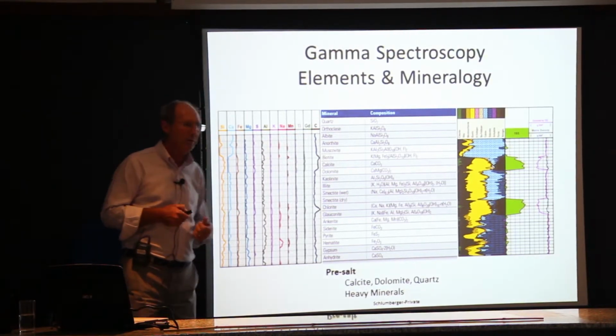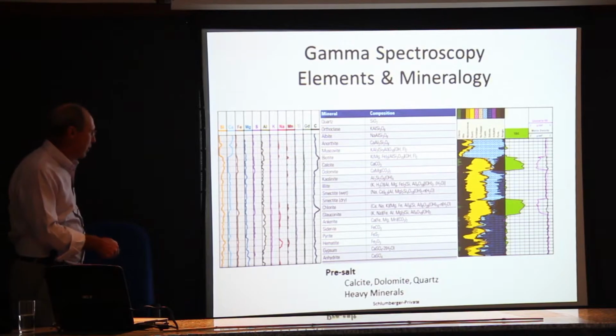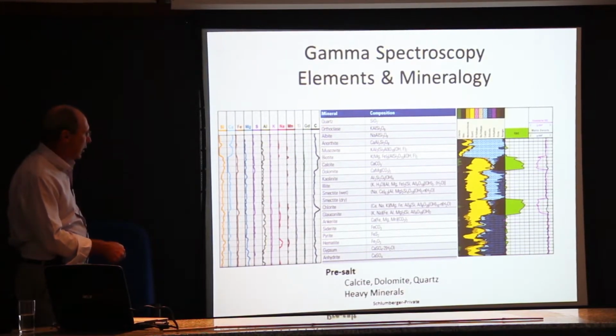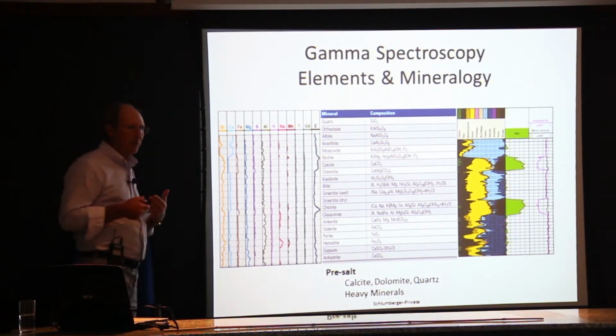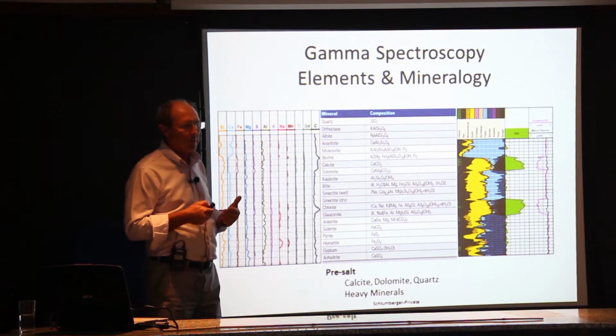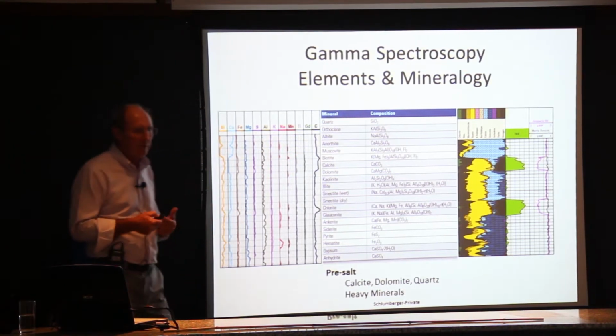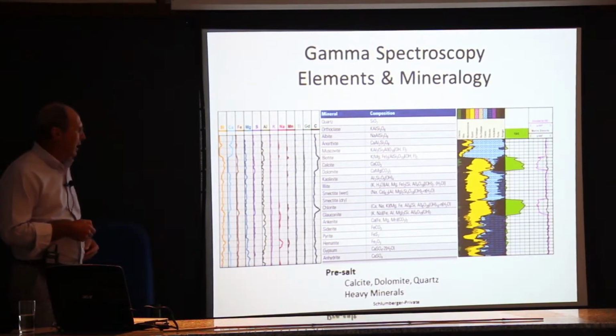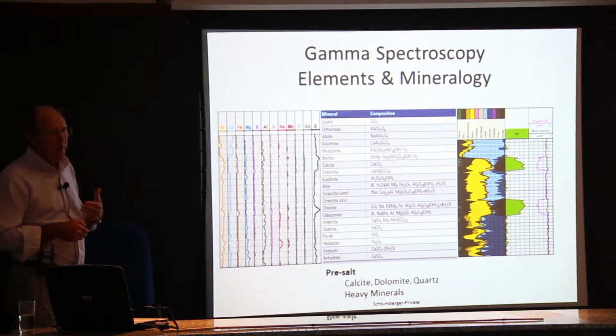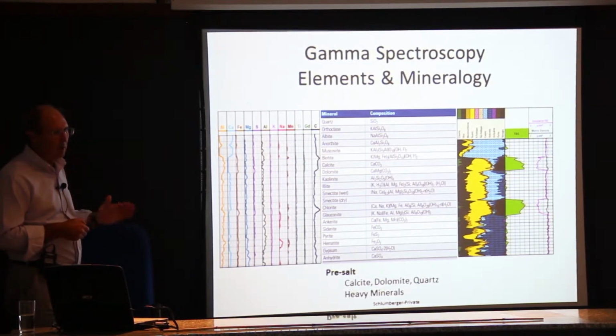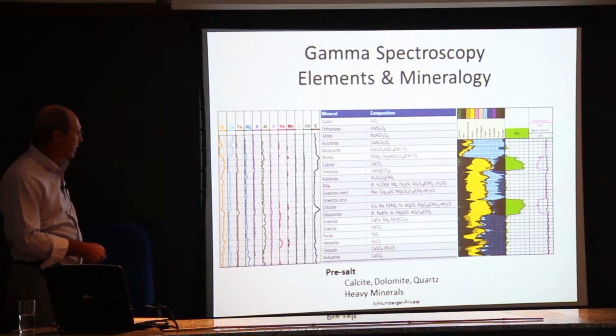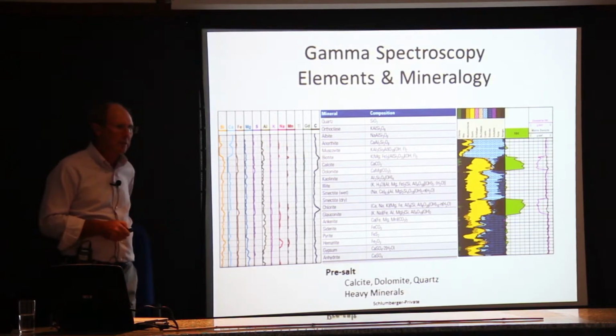Also heavy minerals. Heavy minerals are a big problem in the pre-salt. Siderite, pyrite, hematite. These are iron-rich minerals, and it only takes a small amount of these iron-rich minerals to have an effect on the density and even the neutron logs. And that is one reason why Petrobras in particular really likes to use the NMR logs as a porosity indicator, because even when you have, say, less than 5% of these heavy minerals, it can have an effect on the density neutron log.